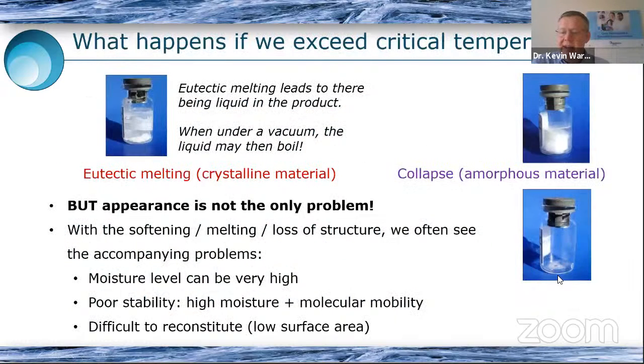The vial below it, sorry, let's go back. The vial below it here, you can see that the product is now completely at the bottom of the container. Now this is the glucose that I mentioned before, so it will collapse just below -40. So if you exceed that temperature, all of your glucose will end up effectively as a syrup at the bottom of the container. Now, believe it or not, these two vials on the right contain exactly the same amount of material, about 100 milligrams. But you can see that at the bottom here, it's completely collapsed. So it has virtually no surface area, maybe a couple of square centimeters, whereas hopefully the one at the top, well, we might be talking in terms of square meters per gram. So it's actually quite significant. It can be a very big difference.